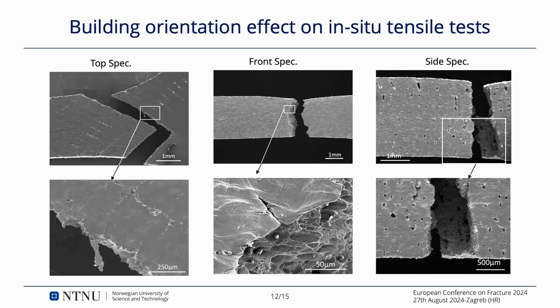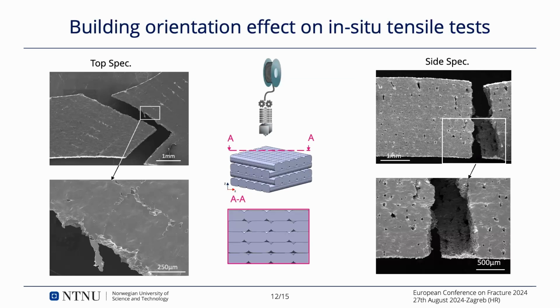First, you can understand what is the printing strategy that we used, which is a classic plus minus 45 degrees. And in the case of the top specimens, basically, the fracture just followed the easy path of the interface between rasters. That means that the adhesion between rasters is not sufficient, clearly. Then we can jump to the side specimens. Here, the issue was that, as you can see, there is quite a lot of porosity, and the porosity pattern comes once again from the printing strategy that we obtained.